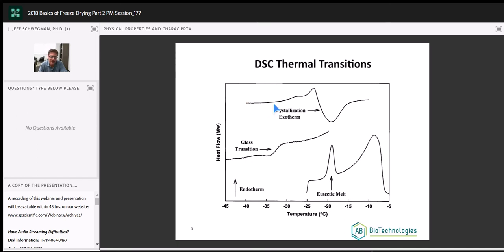This tells me a couple of things. It tells me my potential annealing conditions, so I want to be above this. I want to be annealing somewhere right around here, whatever that temperature is. I don't want to get too warm because I don't want to melt the ice, there's still ice present in this formulation, but I want to get through the glass transition, crystallization event, so this would be a good temperature for annealing.